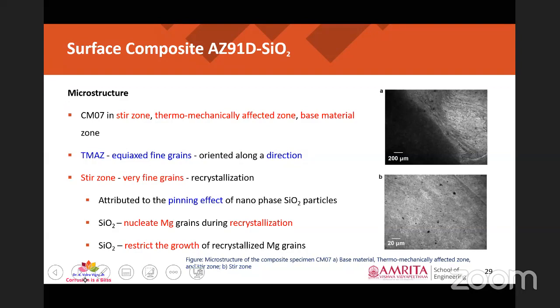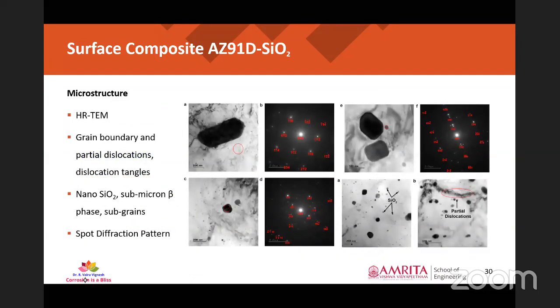We could just see it over here, the images from high resolution transmission electron microscopy. Here we could observe the grain boundary, partial dislocations and dislocation tangles that are present in the material. We could literally observe the nanophase silica particles and submicron beta phase particles that are present in the matrix in a completely dispersed manner. So friction stir processing has helped us a lot in breaking and fragmenting this beta phase network and ensuring that we have subgrain formation too. This subgrain formation is very much essential for improving the mechanical properties of the material.